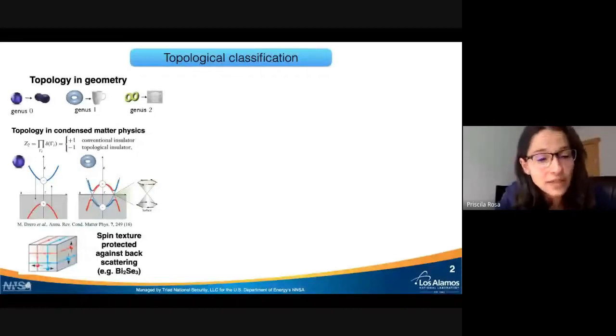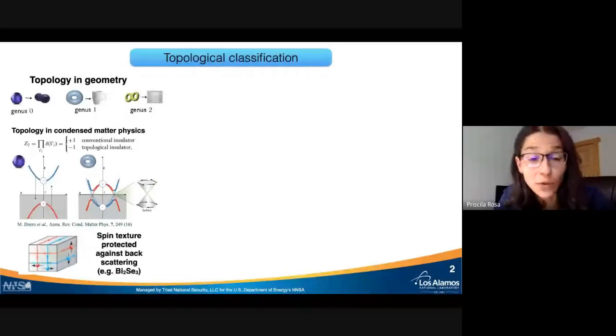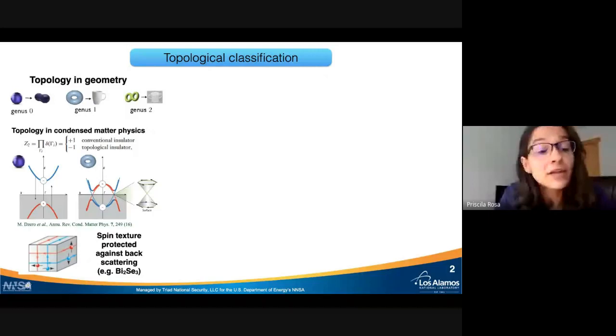So some interest is there because of, for example, spintronics. But I think the main important aspect that really got people excited about this is that you can, in principle, have this topological insulator state in proximity to an s-wave superconductor, and that will give rise to exotic quasi-particles called Majorana fermions, and I'll get into this in a little bit. These particles are really elusive. There is no evidence that they exist, but there's still a lot to be done.